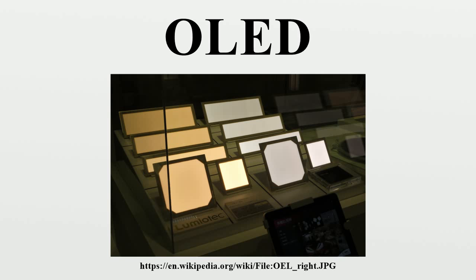Phosphorescent materials. Phosphorescent organic light-emitting diodes use the principle of electrophosphorescence to convert electrical energy in an OLED into light in a highly efficient manner, with the internal quantum efficiencies of such devices approaching 100%. Typically, a polymer such as poly(n-vinylcarbazole) is used as a host material to which an organometallic complex is added as a dopant. Iridium complexes such as Ir(ppy)3 are currently the focus of research, although complexes based on other heavy metals such as platinum have also been used.